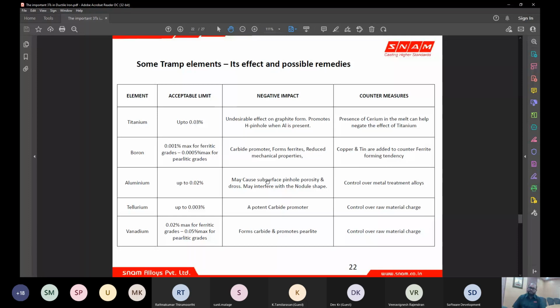And where does tellurium come from? Tellurium comes from your graphite cups, where your CE meter cups have tellurium in them, because the chilling is done there to measure the carbon content. And when these tellurium rich cups, or the sample cups poured for the CE meter check, are put back into the furnace, your tellurium keeps increasing. This is done over a period, and you generally do not have a measure for tellurium in your spectrometer, or your spectrometer might not be calibrated for tellurium.